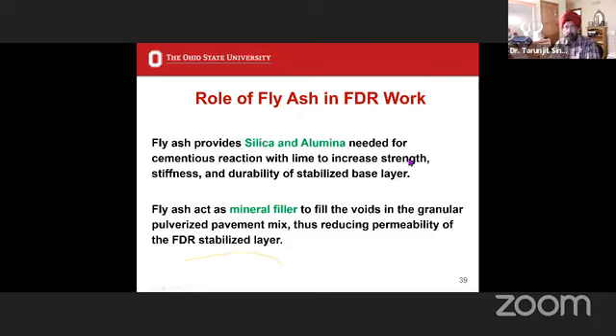So what we are most interested in is stiffness and strength, probably more increase in stiffness than strength, because the lack of stiffness is what typically will cause the failure of rutting for an asphalt pavement, even though it has not failed.